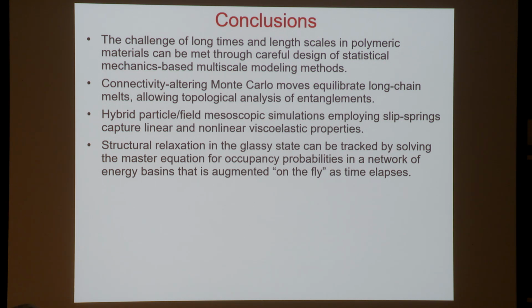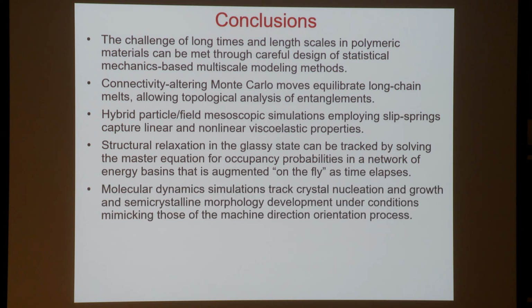And here, this landscape picture of a multidimensional potential energy landscape with many minima basins between which the system can execute infrequent transitions seems to be quite useful. One can design an algorithm that solves the master equation for the population of probability in these basins in a network that is augmented on the fly, and track sub-glass relaxation transitions apparently in agreement with experiment.